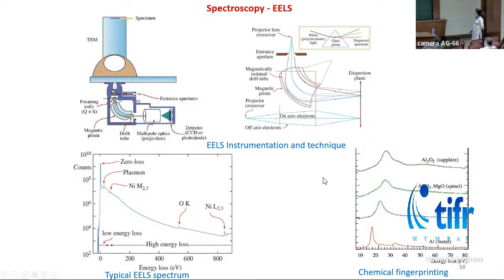And this is the core loss peak region, which can give us information about elements present in the sample. So this is the typical spectra of different aluminum compounds. By looking at this spectra, we can see the aluminum nitride peak has a different position. So by looking at the peak position, we can identify this is aluminum nitride. Sapphire has a different peak shape. So by looking at the peak shape itself, we can identify that this is sapphire in the sample.